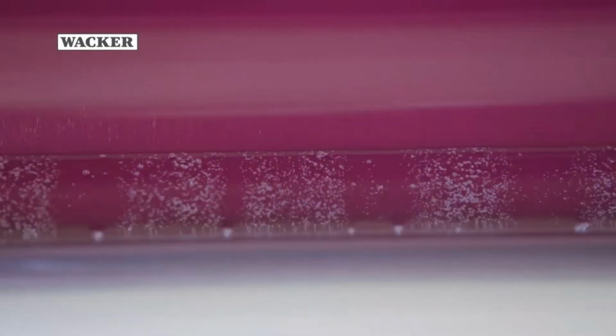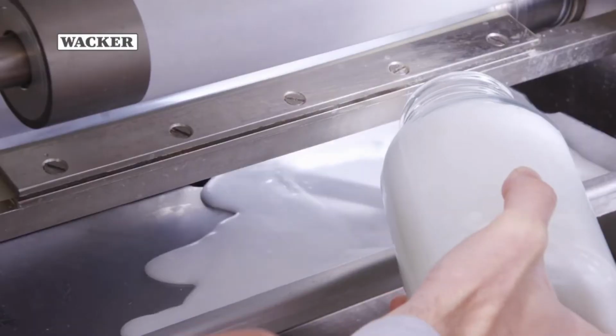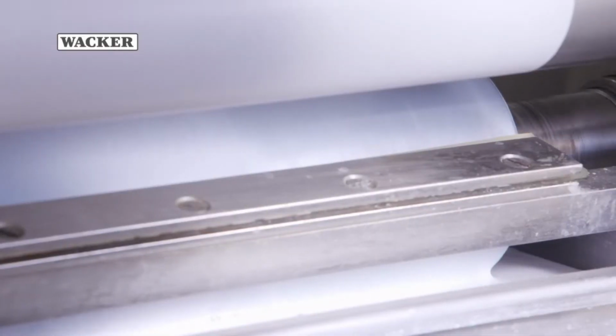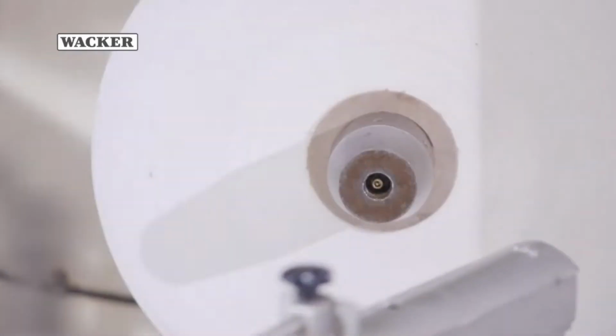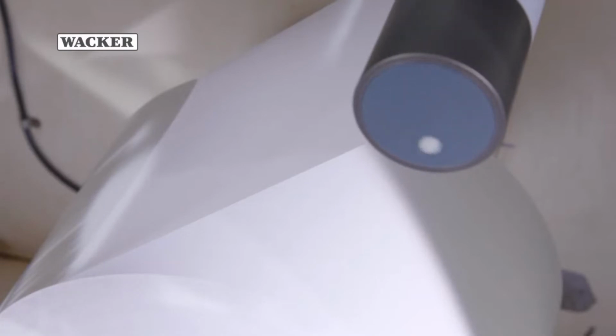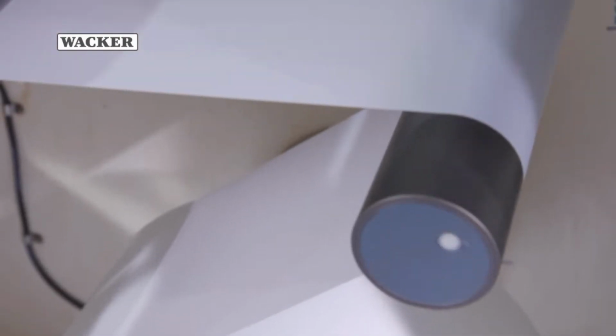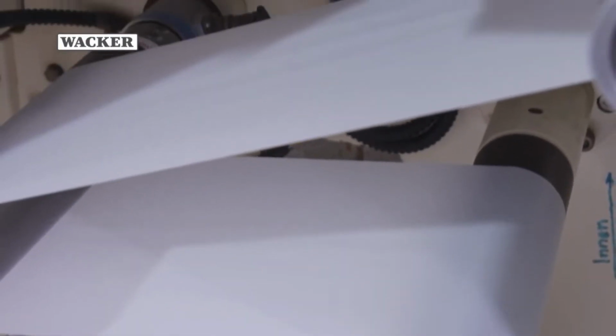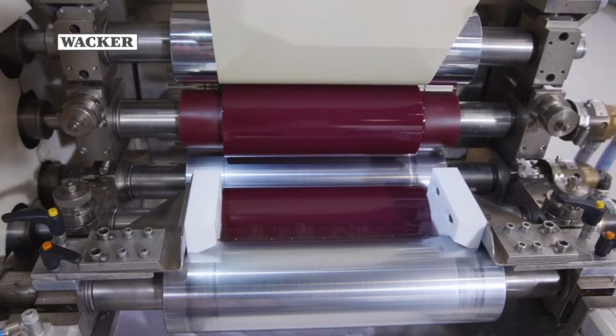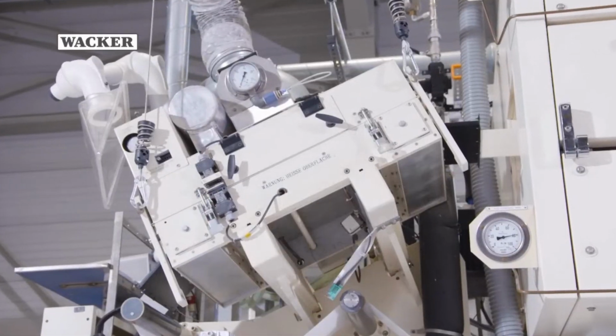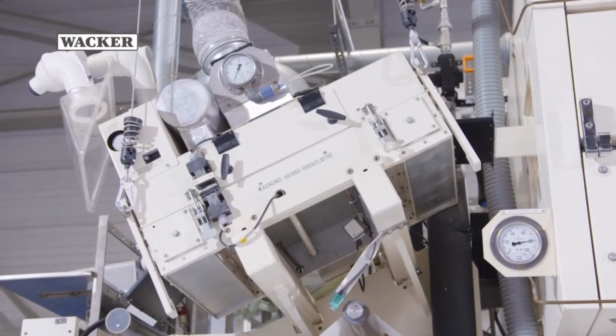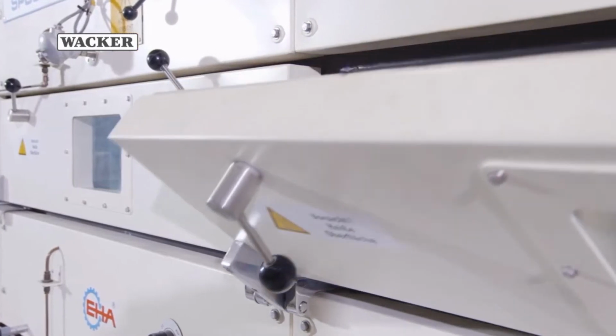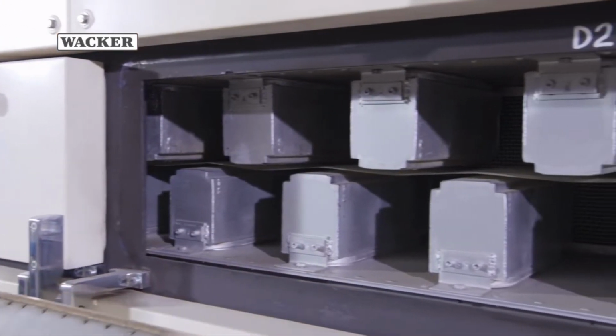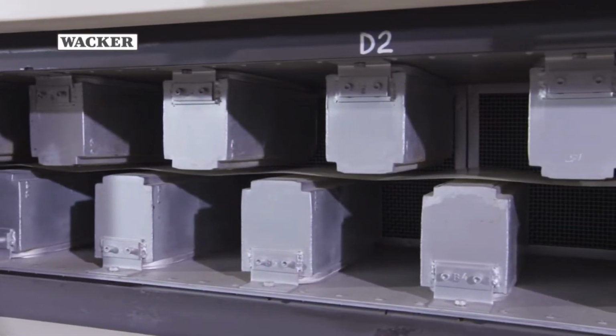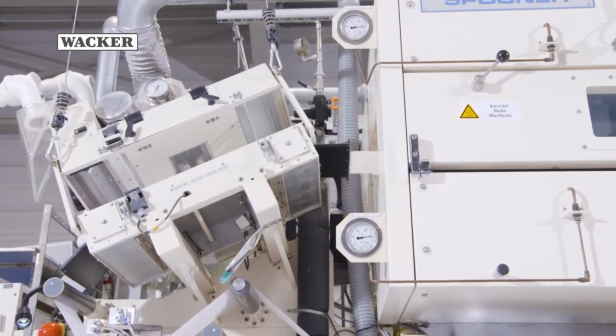The prepared silicone formulation is poured into the coater. Alternatively, an emulsion can be used. Once the backing material has been inserted, the automatic coating process can begin. A film of silicone just 0.6 to 3 microns thick is applied to the particular backing material, paper in this case. The backing material is then fed through an air flotation dryer at a temperature of up to 200 degrees Celsius. The silicone is heat cured here.